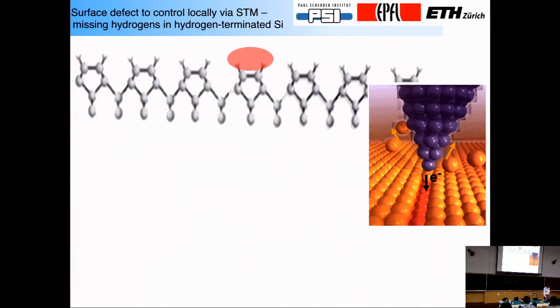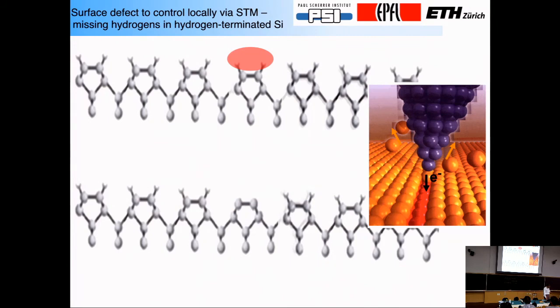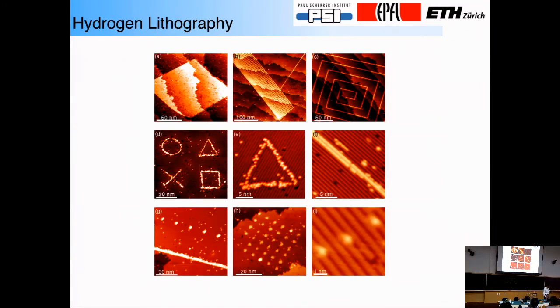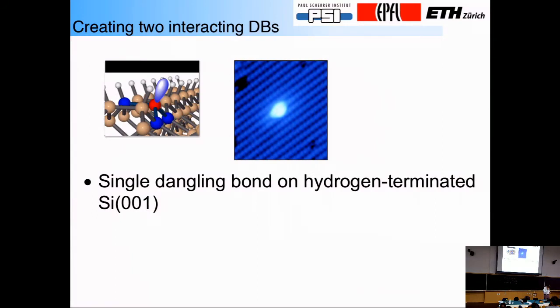So these electrons at the dangling bonds. The way we remove them is with an STM tip. And so if you go through with an STM tip, then you can remove atoms, or pairs of atoms sometimes. And then, in fact, one can do lithography with this removal technique. So you can make all kinds of funny patterns by removing selectively with an STM tip these hydrogens. And now we're just going to talk about the physics that one can do.